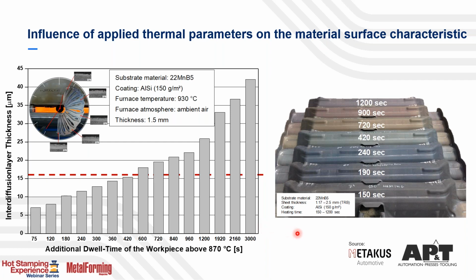You can also see that a little bit when you go into press hardening shops and you see parts with different colors. That is an obvious sign for either having the parts, if you had them for a too short time in the furnace, or maybe a too long time, and you see the change of color. So what we typically want to see, the color is also depending on the final temperature that you're using, but what we typically want to see is this bluish color, basically.